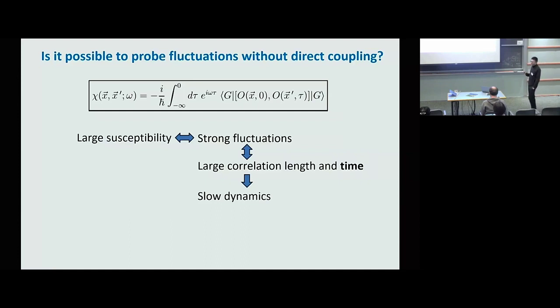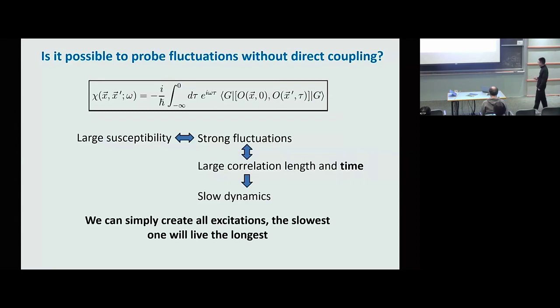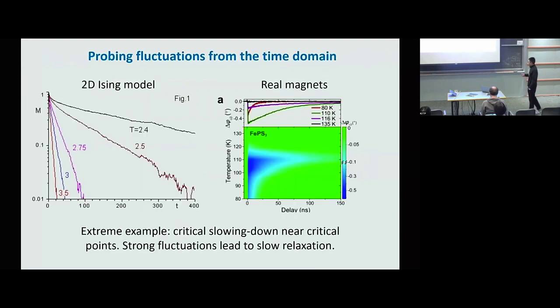But at least, in principle, this tells us it's possible to get some information, some properties of the fluctuation, without directly coupling to it, because we can simply create all excitations, and the slowest one will live the longest. And this will allow us to naturally isolate the ones potentially with strong fluctuations. Okay, so some examples I guess we're all familiar with. An extreme example is the critical slowing down behavior near critical points.